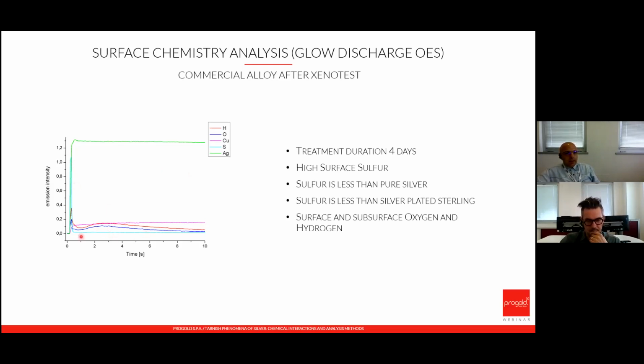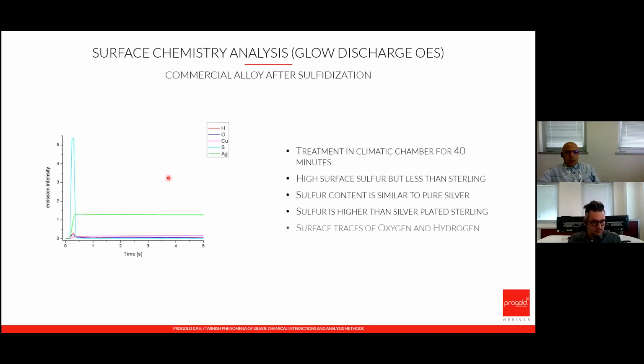Moreover, again, copper seems to be not relevant on the first layer of the surface. Conversely, the direct sulfidization test in the climatic box provided a lower sulfur concentration than traditional sterling, proving again the protective action of the other elements in the alloy, like zinc, silicon, etc. Then it provided the same sulfur content as pure silver and a higher sulfur concentration than silver-plated sterling.